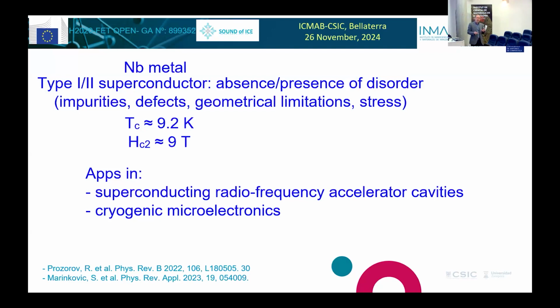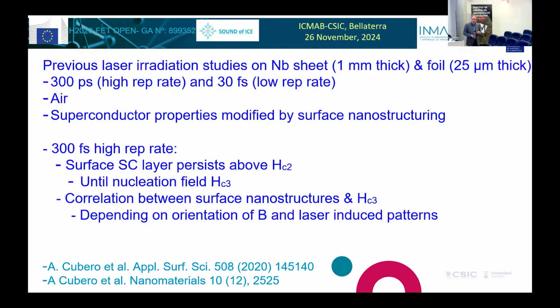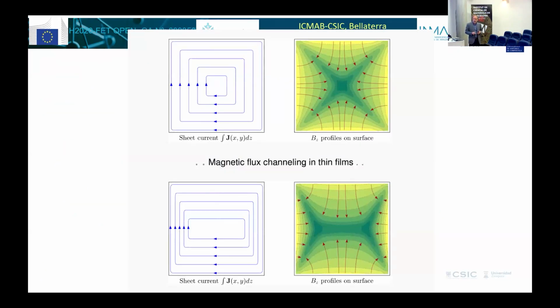The question is, what could we do if we change the structure of the surface and we generate a nanostructure? Does that affect the superconducting properties? Does that affect its use in applications? And so basically, from one of our colleagues, Antonio Badia, who I showed you before, he makes this simulation, and he can see, depending on the geometry, how you apply these nanostructures, and you can get the magnetic flux profiles penetrating into the film.